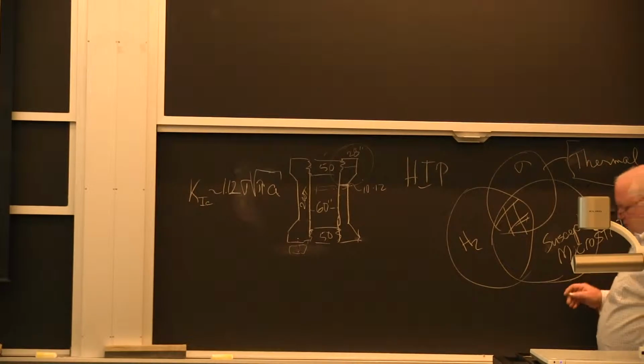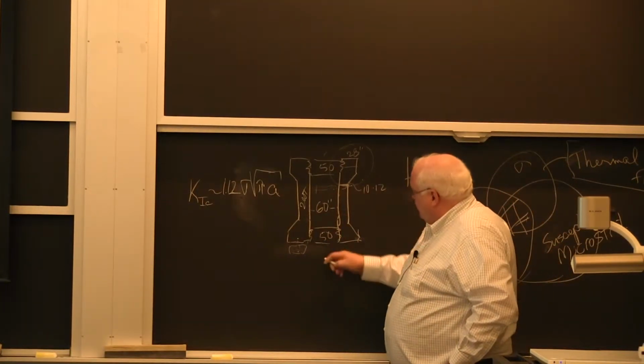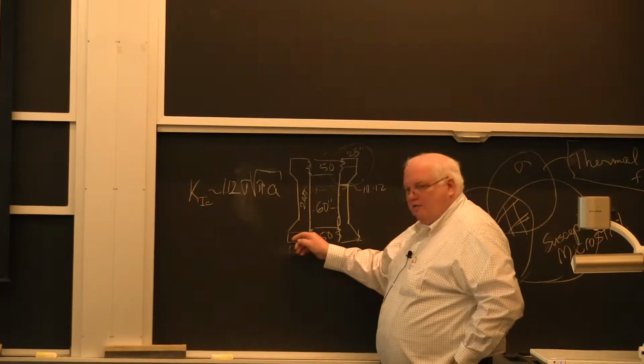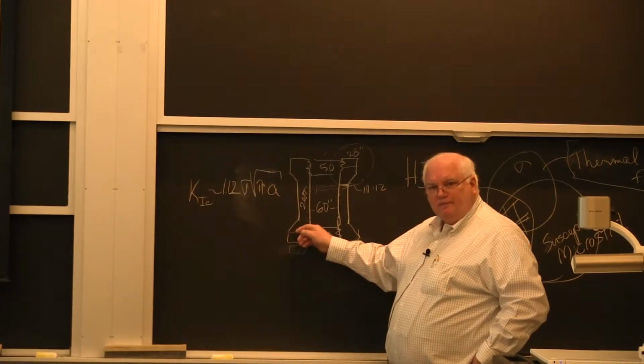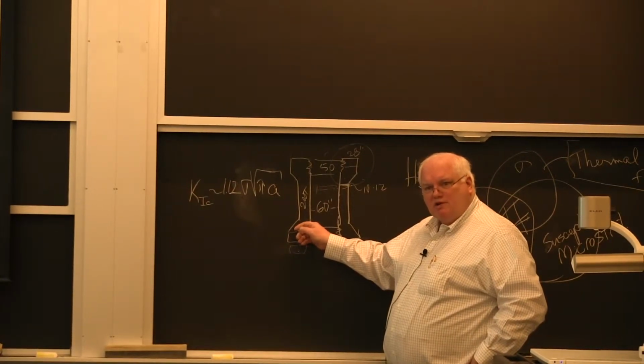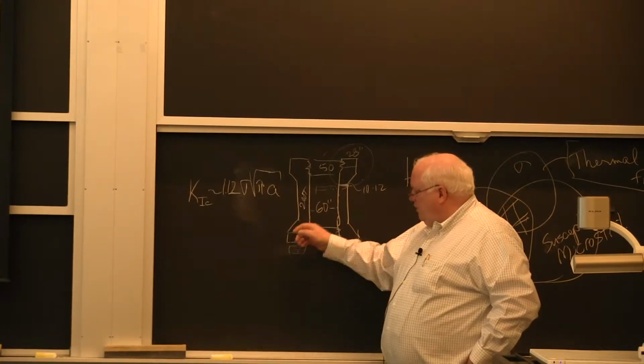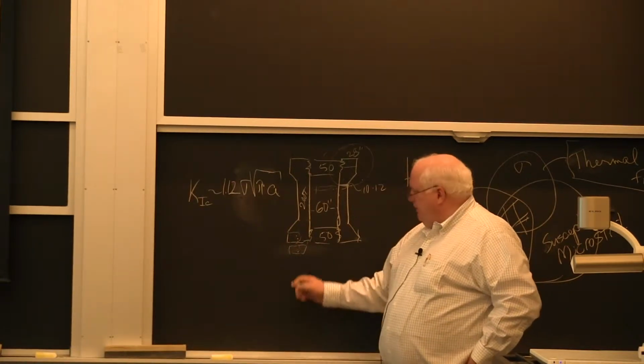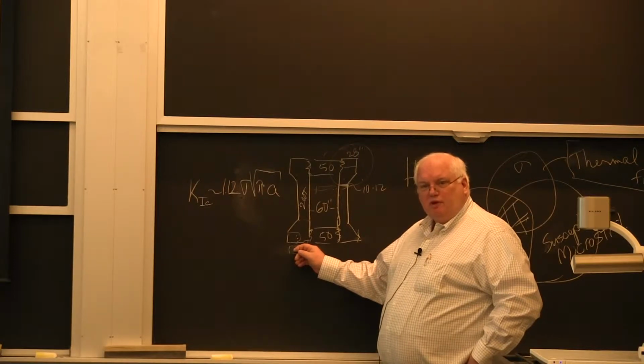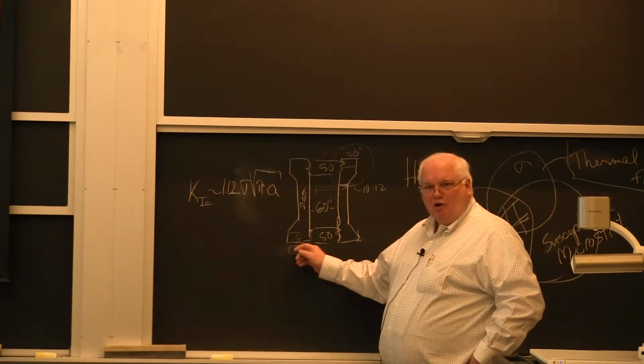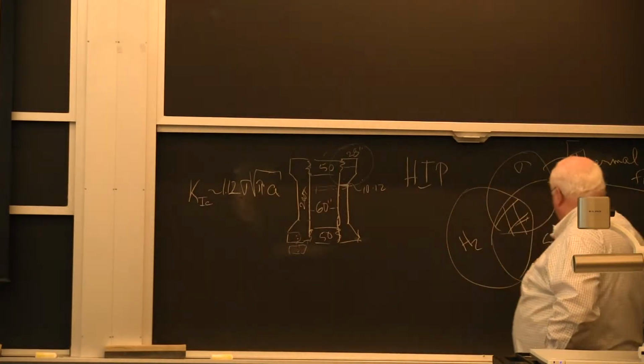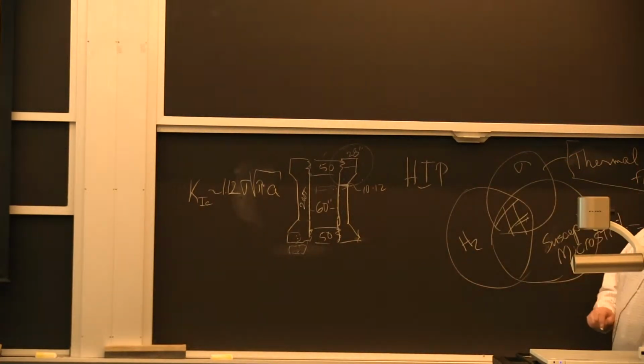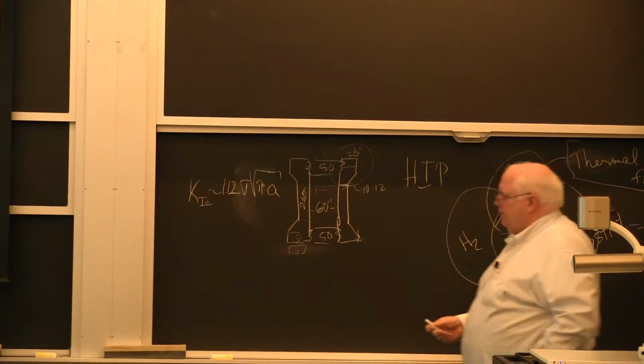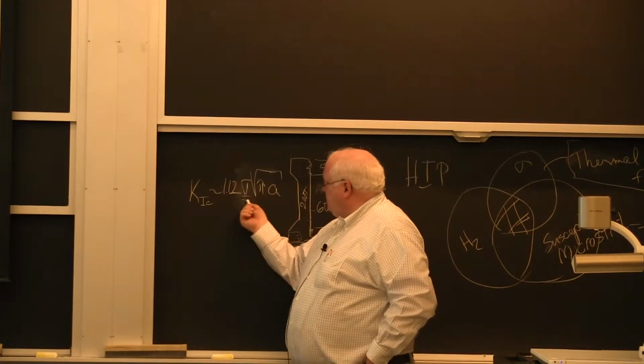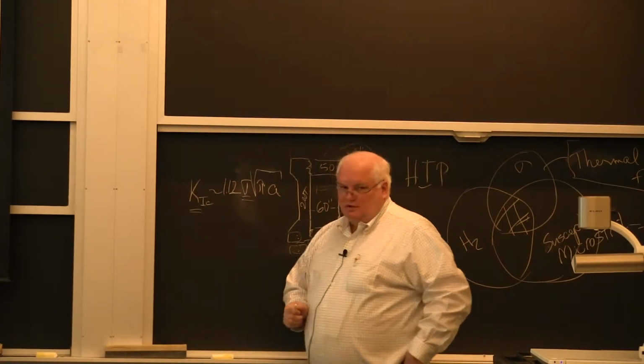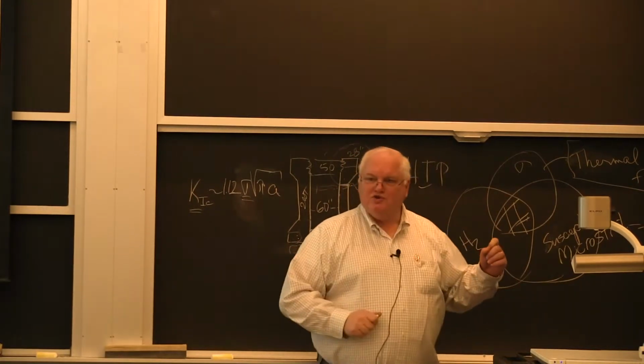The susceptible microstructure, well, it turns out, since the heaters were in here, these little corners down here never had been heated during operation. They still had the same properties as the steel mill. And so they went in and they measured that. And guess what? It was a little bit better than the first one that failed, but it still failed by a large margin. So they had lousy toughness. So if you want to talk about susceptible microstructure, you have bigger stresses, you have lower toughness, and then where did the hydrogen come from?